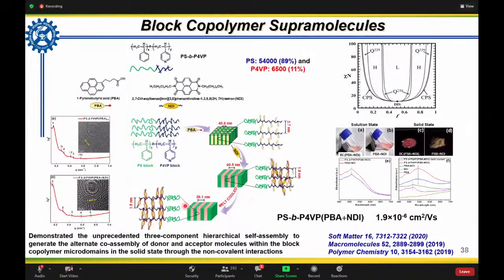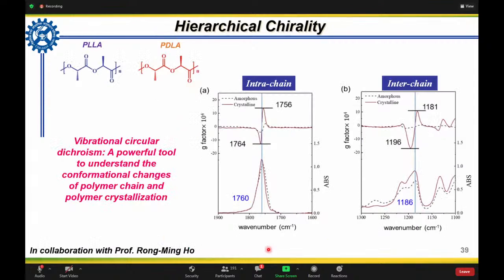So this is one example. In this case, we have used an amorphous block copolymer, where we have a pyridine group. By exploiting this, for the first time, we have demonstrated the multi-component assembly, because in the literature only a block copolymer and a small molecule have been explored. But in our case, we showed a multi-component assembly using hydrogen bonding and also pi-pi interactions. So we could assemble donor and acceptor molecules within this block copolymer morphology very effectively, and we could demonstrate that the charge carrier mobilities can go even up to 1.9 times 10 to the power of -6. Later, we have done one more work by introducing functionality for the acceptor molecule also, and those are very similar to conducting polymers.